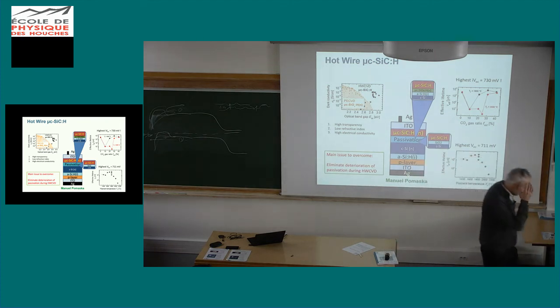Yeah, if you go a little bit into the detail of the TOPCon technology, so how you make this poly layer, you make it at high temperature, and then at high temperature, all the hydrogen that is possibly there went away. You know these problems also if you're going over that with your laser. And hydrogen is essential in passivating any defect that you have at the silicon interface. So if the hydrogen is gone, your passivation is gone. So on that level it really matters, at a very low density of defect states at the interface.